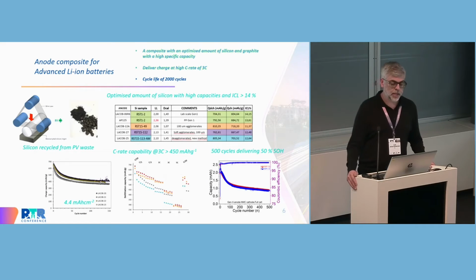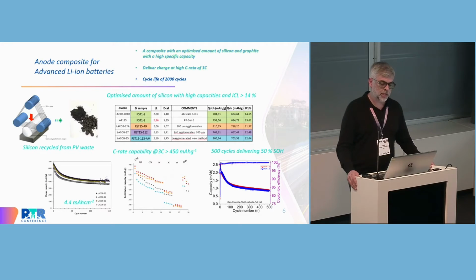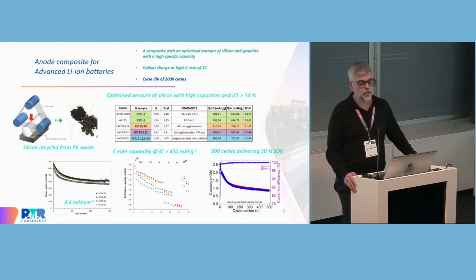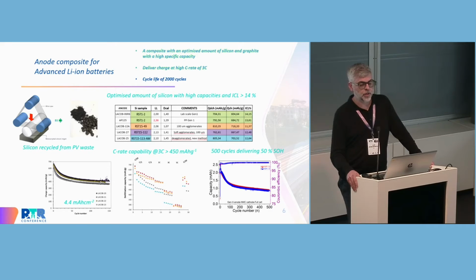For the anode, we were looking at recycled silicon from the PV industry, which was challenging from the beginning, but also very interesting for improving the sustainability of the batteries. We looked very carefully at the processing conditions of these silicons, and we managed to get high loadings, which is important for high energy density, beyond 4 milliampere hours per square centimeter, so that was a good achievement as well. We reached a silicon loading of between 10 and 12 weight percent in the electrode. At those weight ratios, we managed to get capacity at 3C, which was also one of the objectives of the COBRA project. Unfortunately, as my colleagues have already shown, the cycling degradation of this silicon is quite severe.